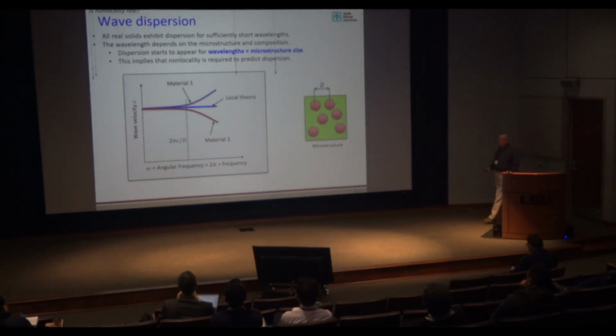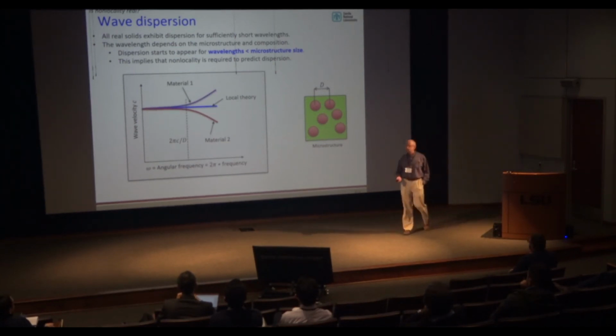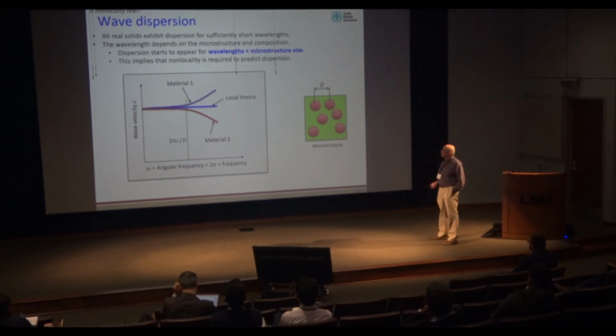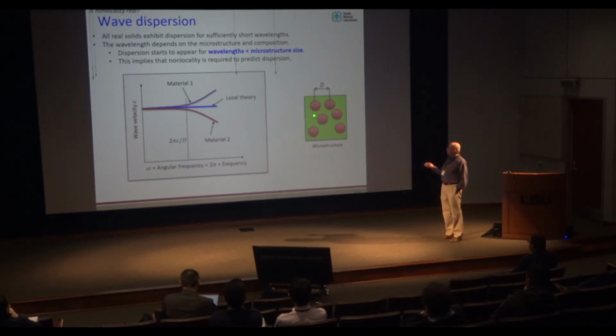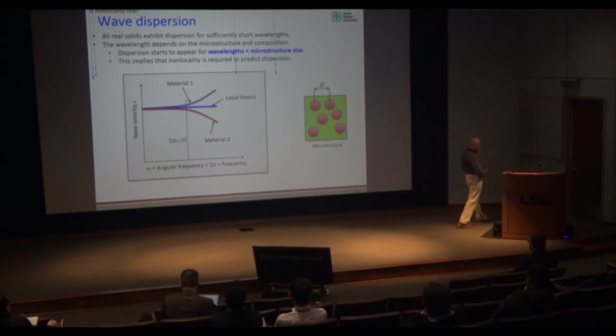Wave dispersion is another opportunity to use experimental data to derive non-local material properties. So what wave dispersion is, is changes in wave velocity as either the frequency or the wave number are varied. So in materials with a microstructure, dispersion curves for waves that have wavelengths on the order of the microstructure size or less will show features on a dispersion curve. The waves will go either faster or slower, depending on the details of the material, than longer wavelength waves.